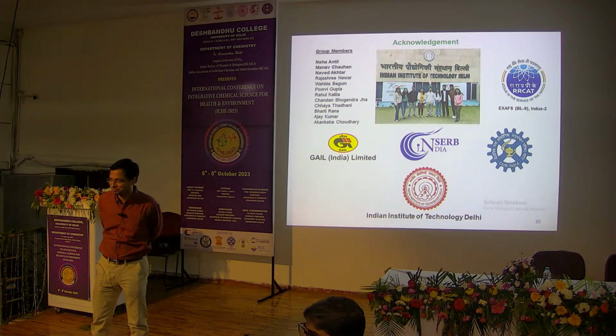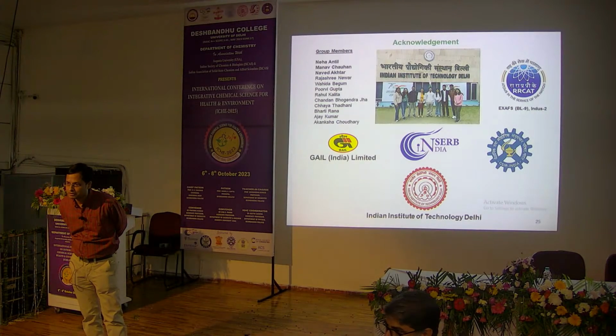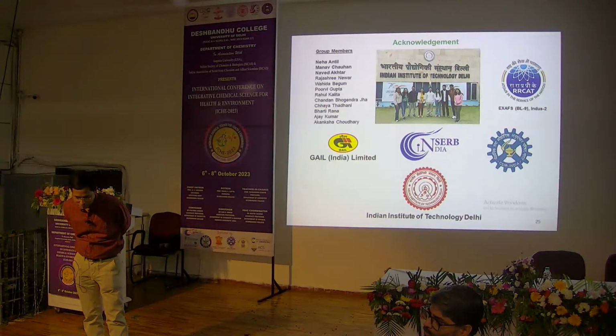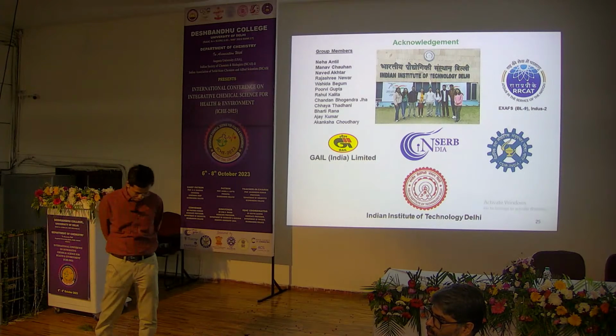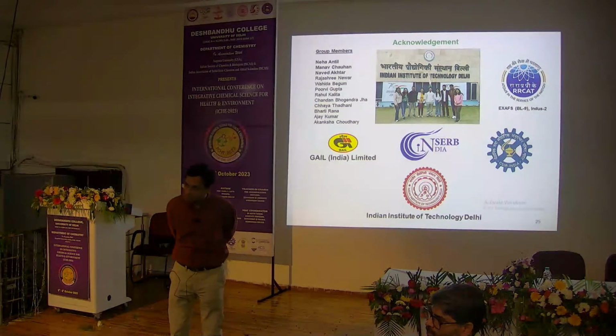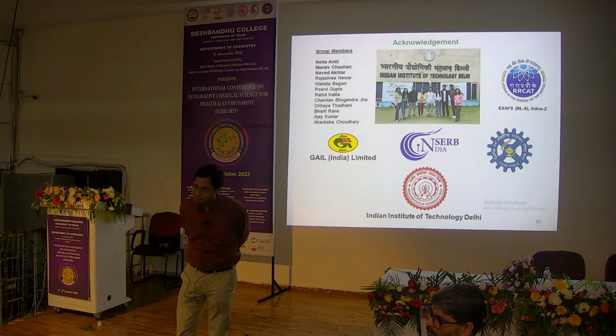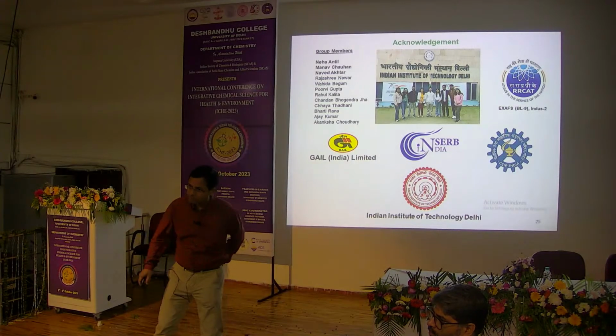Thank you. Very interesting lecture and very good work. I just want to know, you have made this cerium MOF, then you have added this copper. And in that step, you have used N-butyl lithium. Did you check this reaction without N-butyl lithium? It is necessary to take the N-butyl lithium because the hydroxyl group is already there, but you are taking copper one. So without N-butyl lithium, the reaction will not happen?